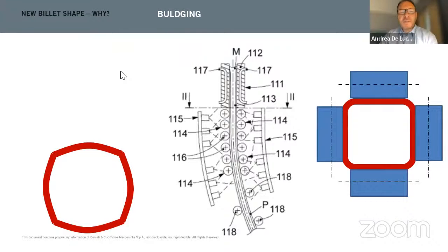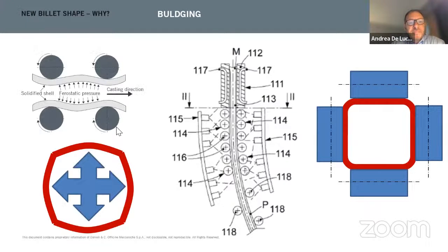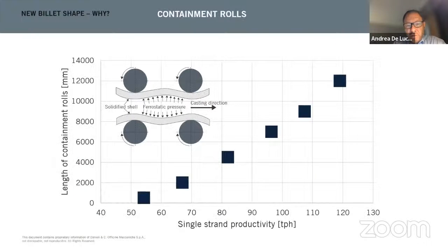Okay. So the square billet is bulging and the shell bends. To counteract this phenomenon, what is used is adding containment rolls at the exit of the mold, like in the thin slab caster. But this introduces some complication, cost, and difficulty to maintain these conditions. And the more the productivity of the caster increases, the more length of rolls you need. For 80 tons per hour, you need 4 meters of containment rolls. From 100, you need more than 8 meters.